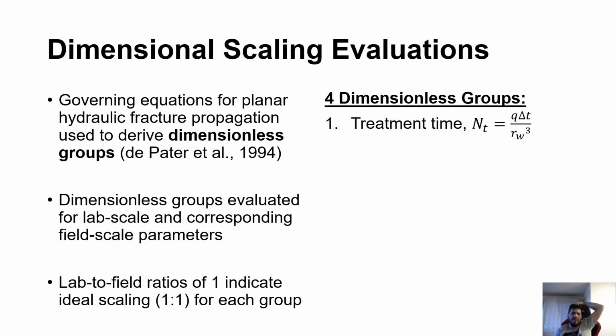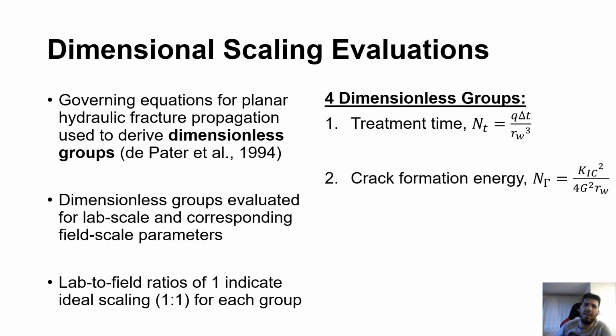The first one is the treatment time, N sub t, equals the injection flow rate Q times the injection time duration delta T divided by wellbore radius R_W to the power of 3. Then we have the crack formation energy, N sub gamma, which is equal to the critical stress intensity factor for mode 1 cracks, K1C squared, divided by 4G squared R_W. G is a modified version of the bulk modulus that de Pater shorthanded to make the derivations easier to follow and cleaner. It still has dimensions of PSI, of pressure, and he called it the fracture propagation modulus.